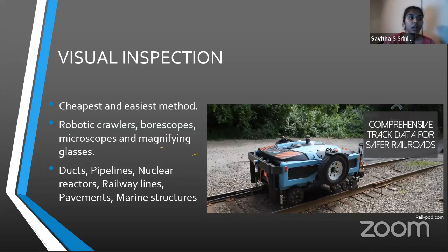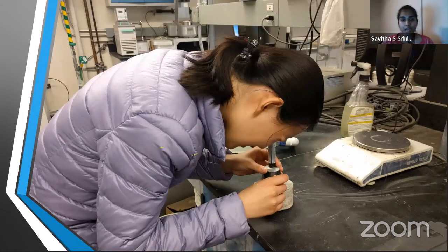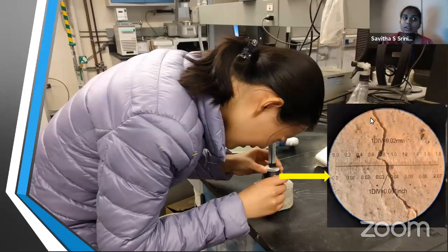So what I have here is a picture of my undergraduate assistant demonstrating how to use the crack microscope. So you can see what a crack would look like, and also see what the width of these cracks would be using just a simple crack microscope. You can take it to the field and do your measurements right there.